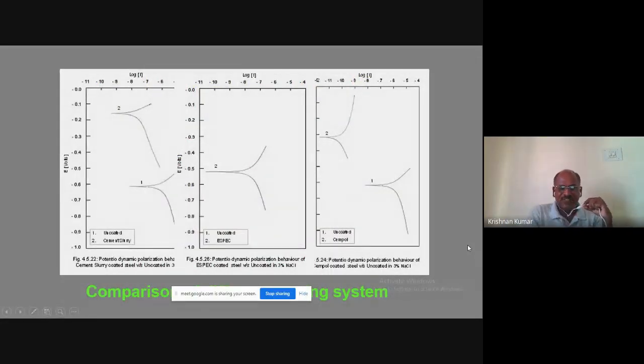Now, we have extensively studied this during the development. You can see number one is uncoated, and number two is cement slurry, which is an inorganic type of coating system. It's a highly passive system. When this system is applied on the concrete surface, what is happening? This is the polarization curve. For the uncoated, the corresponding E value is nearly 0.7 to 0.8. But when you apply the cement slurry, a highly passive system, it shifted to more anodic. That means passive: if it goes more anodic, it is passive.